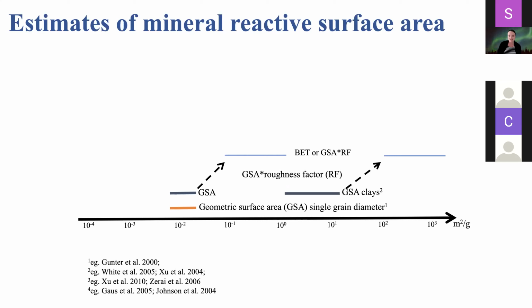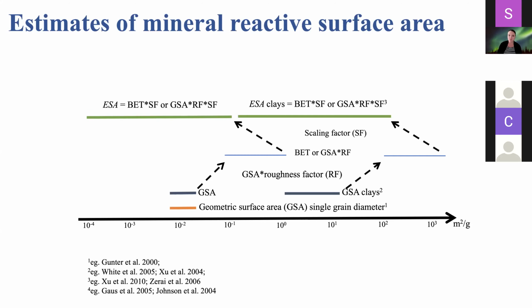The challenge here is that we have seen some evidence in the field that only some sites are potentially reactive. So we account for that by applying a scaling factor. This can be anywhere between 1 to 3 orders of magnitude. And this is an effective surface area. This scaling factor is sometimes also applied directly to the geometric surface area. And so now you can see we have a huge range of potential surface area values that we've estimated to use in our numerical simulations.